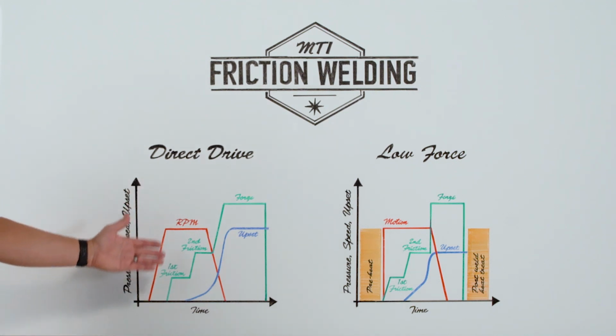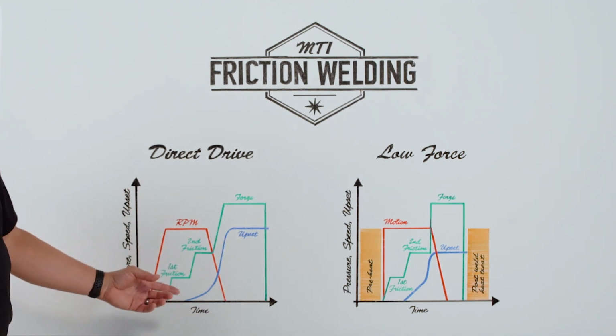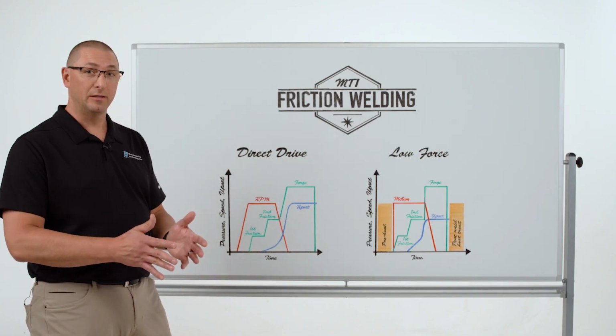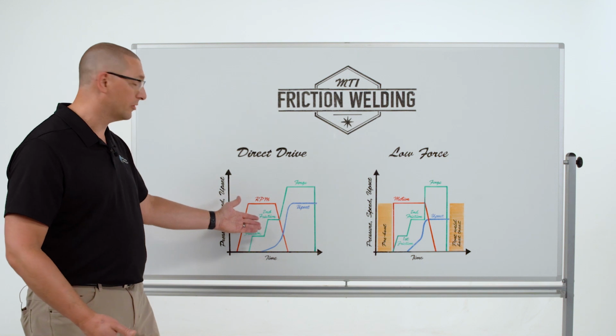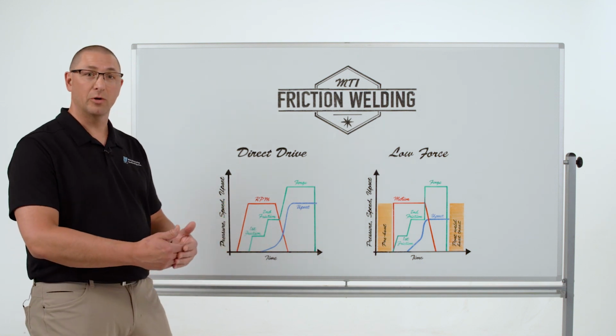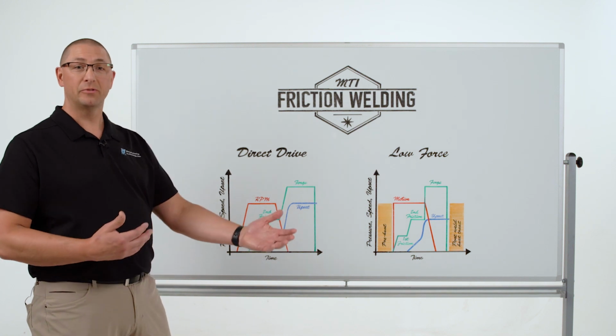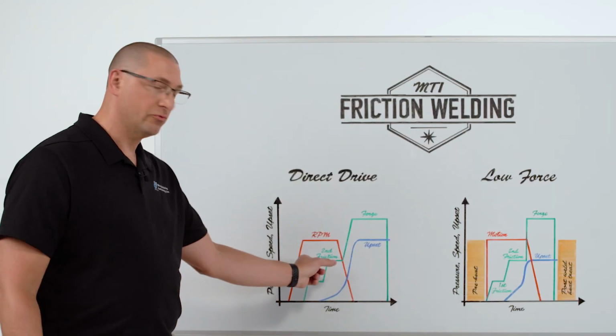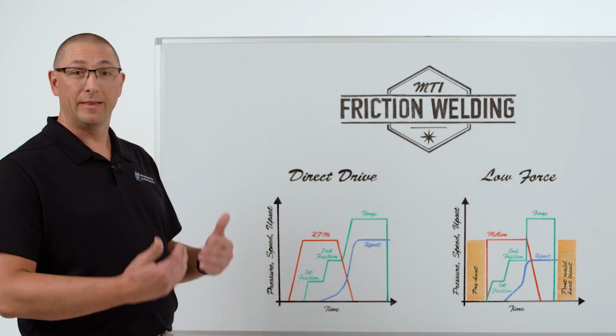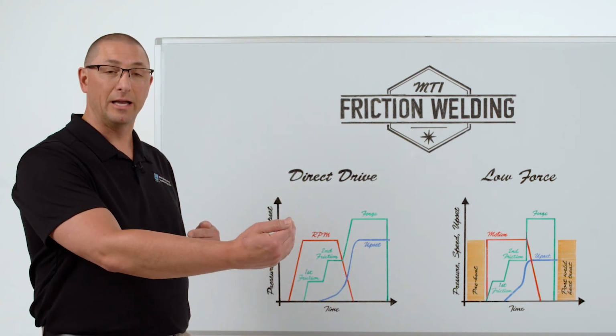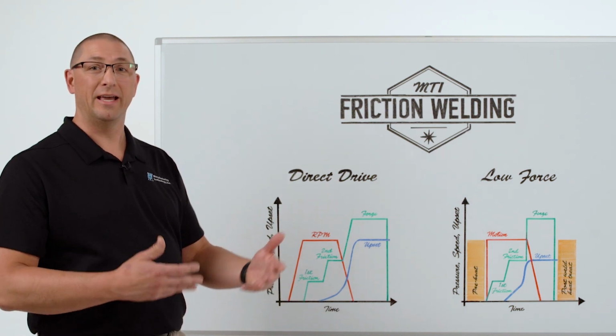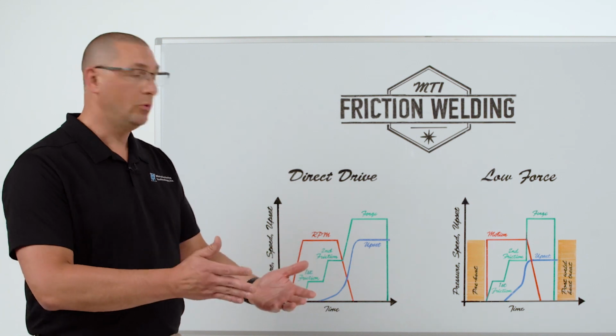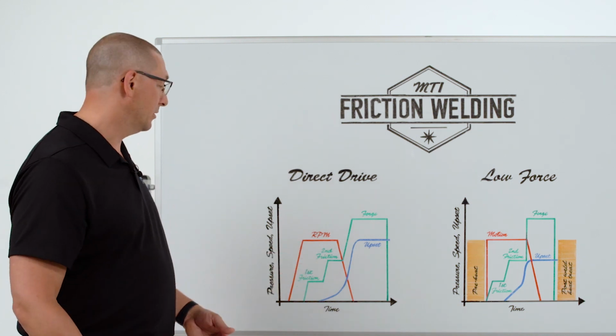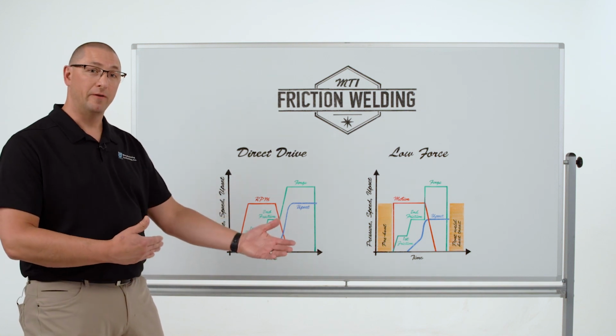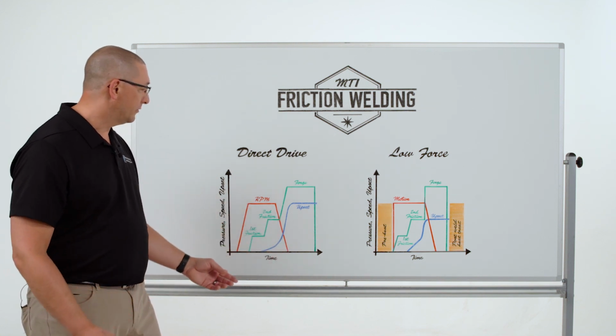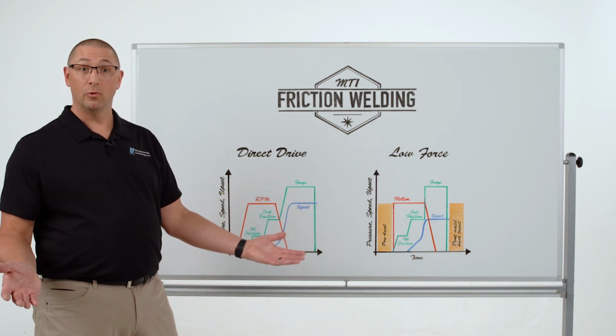We bring the eye or the clevis up to a rotating speed, the RPM. We bring on first friction pressure. This squares up the interface a little bit, reduces the coefficient of friction so that we can bring on greater load. The second friction phase is where we add the majority of the heat and we start upsetting the material. This friction phase is shown as really short here in the diagram, but in the case of hydraulic cylinder rods, we extend this time and we get a lot of upset in this phase, again, to be able to build heat in the part so that it cools at an appropriate rate to avoid the formation of martensite. Once we get the desired amount of upset, we bring the rotating spindle down to 0 speed, we bring on the forge force, and the weld is complete.